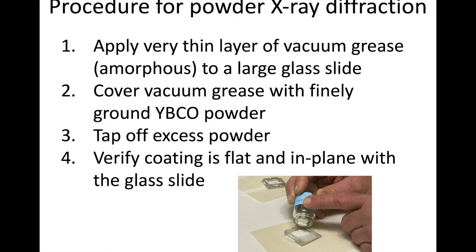I have a video showing how we actually prep the sample for XRD. There are multiple ways to prepare powder XRD samples, but the way we use is to take an amorphous substrate — in this case a glass slide — and apply a very thin layer of amorphous vacuum grease. The idea is that this grease causes the YBCO powder to stick, creating a very thin coating for analysis. Since everything else is amorphous, it won't affect the results.